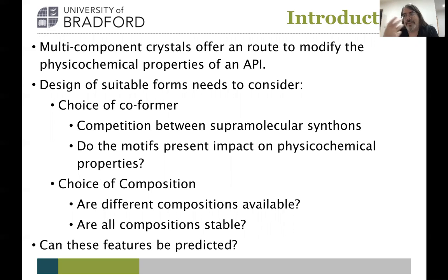What does the competition between the different supramolecular synthons entail? Does the choice of synthon have a direct effect on the physical chemical properties? Another thing that doesn't get quite so much study is the choice of composition. A lot of the materials are made as 1-to-1 ratios, but if it's possible to make a 2-to-1, 1-to-2, or some other composition, does that give us superior properties, superior behavior? And the great goal would be: could we possibly design and predict these things before making them?